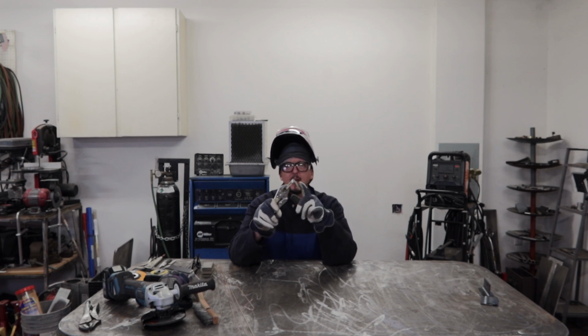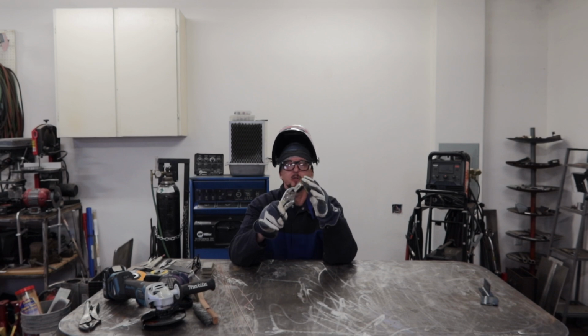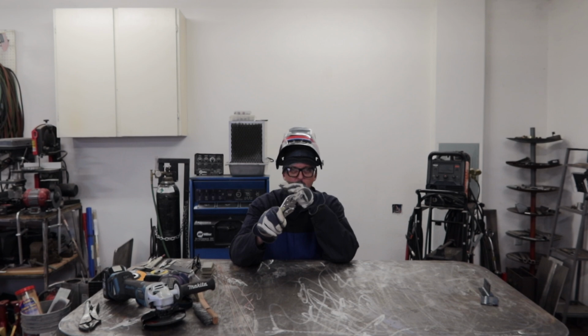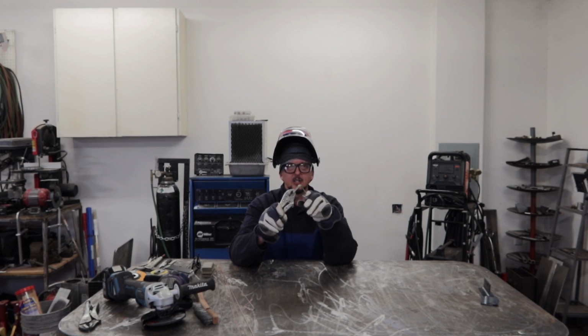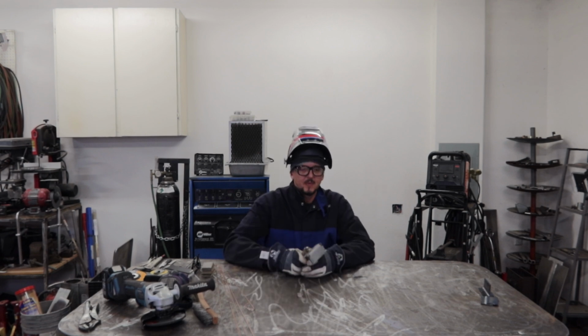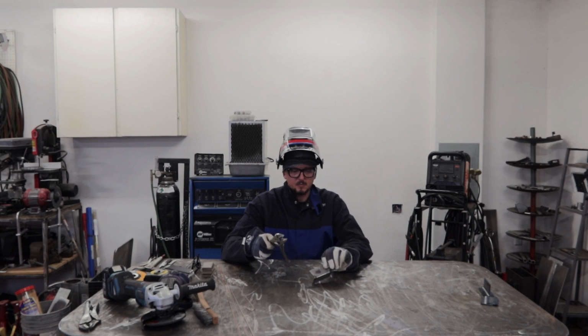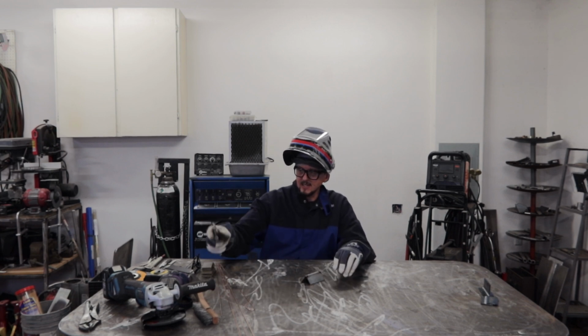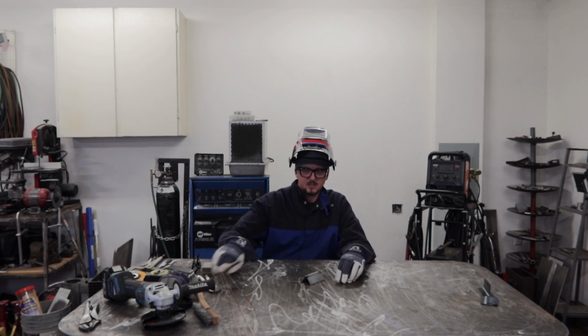So we don't need a lot of filler in order to fill this small area in the center, and we don't need a lot of amperage. If we use too much amperage, then it starts to really melt away these edges and we get sort of a rough undercut look to the edge of this joint. So if we do it right, it should be nice and rounded and smooth. Okay, so that's my settings and what I'll be using in terms of filler metal for the corner joint.